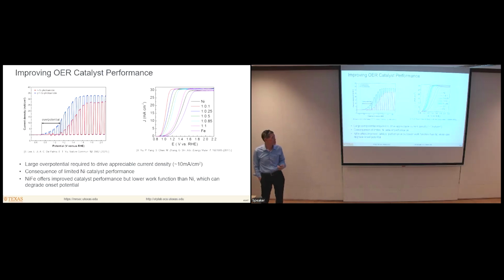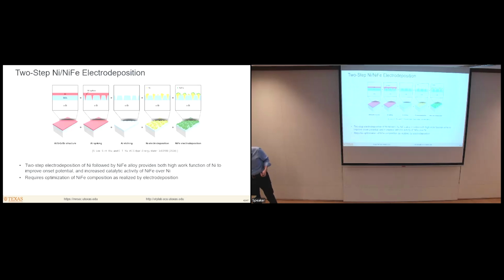That's bad for efficiency. The reason this happens is because nickel is a mediocre catalyst for the oxygen evolution reaction. You can do much better with nickel iron alloys. However, you still want nickel to be in contact with the silicon because that gives you a higher Schottky barrier, and that improves the onset potential. So what you really want is to have a 2-layer catalyst structure with nickel in contact with the silicon, and then nickel iron acting as the catalyst on top.